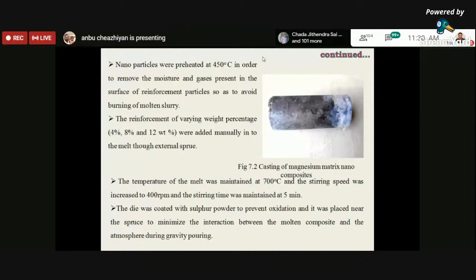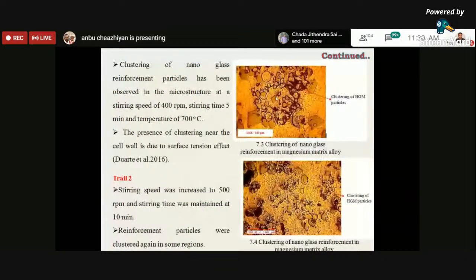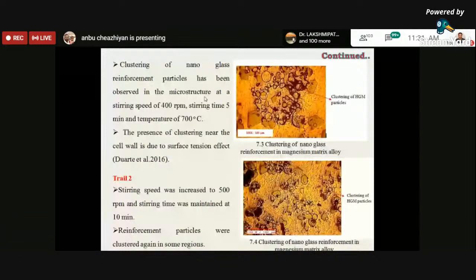These are the things that we observed by seeing the microstructures. Clustering of nano glass reinforcement particles was observed in the microstructure at a stirring speed of 400 rpm, stirring time 5 minutes, and a temperature of 700 degrees centigrade. The presence of clusters is due to the surface tension effect. So it was decided to increase the process parameters: stirring speed, stirring time, and temperature. The stirring speed was increased to 500 rpm, and the stirring time was 10 minutes, but again the reinforcement particles were found clustered in some regions.